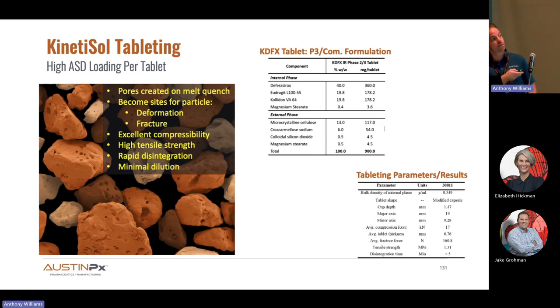So we were able to get 50% drug load in the ASD, and then this ASD produced a viable tablet with, what do we have, 80% of the ASD in the final tablet. So we have a 360 milligram dose in a tablet that weighs 900 milligram total weight. So that's a pretty significant payload for an ASD product.